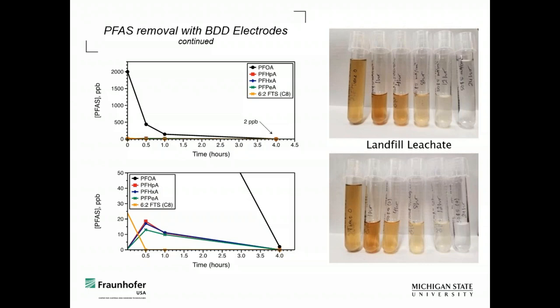Again, this is water that would not be used as a drinking water source. The limit in Michigan is 12 ppb, so this is good enough for use for that specific application or niche in the state of Michigan. As you can see down here at the bottom, here is 7, 6, and 5 of the carboxylates. So in a half hour, we generated about 15 to 20 ppb of those. And then, again, by 4 hours, those were completely gone.